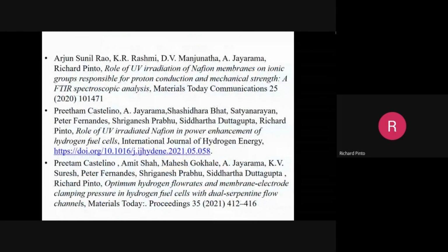Okay, this is of course a Materials Today Communications. It explains the effect of coating and the effect of UV exposure using evidence for sulfonic acid groups, which are shown by FTIR spectroscopy analysis. Sulfonic acid groups increase with UV exposure. And this is, of course, work on the hydrogen fuel cell, these two. Pritham has worked on this.